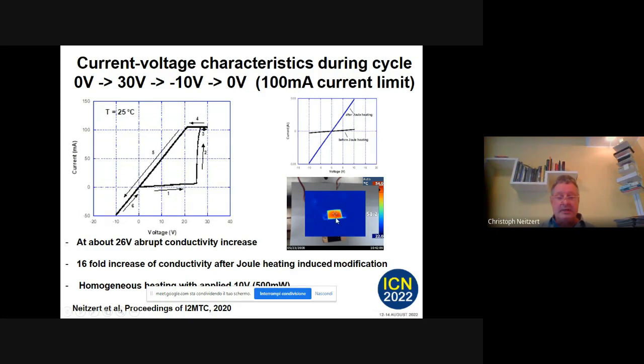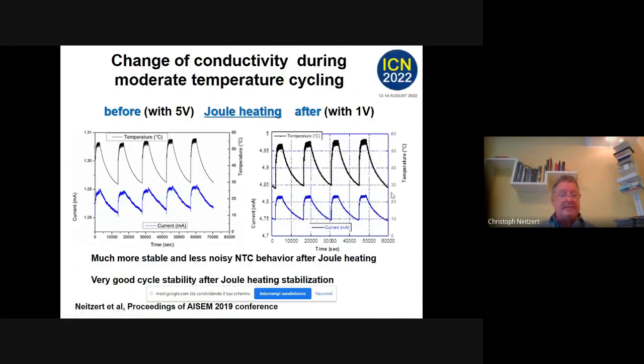We have a good homogeneity. We measured the heating with an infrared camera. If we go for 10 volt, we have about 500 milliwatt. It's a nice heater. Now we want to see, can we use it as a temperature sensor? So we made temperature cycling. Normally we heat about 1 hour and we let it cool 3 hours. During the cooling period, we are in equilibrium with the sensor.